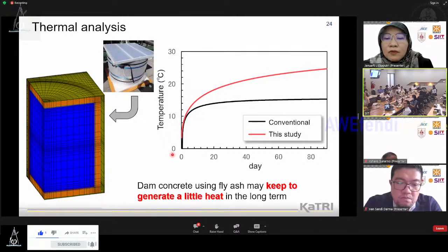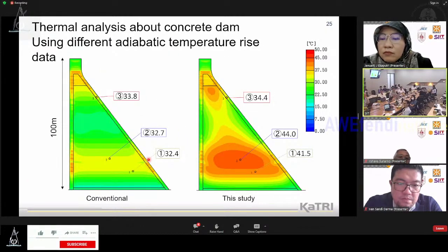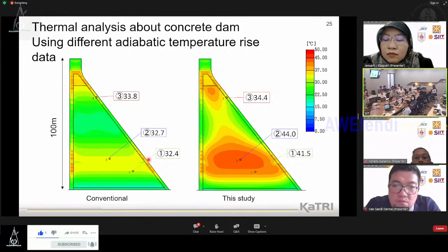The black line is the conventional data, and the red line is the data we got in this study. Dam concrete using fly ash may keep generating a little heat in the long term, I think. So finally, this is a thermal analysis of a concrete dam using different adiabatic temperature rise data.